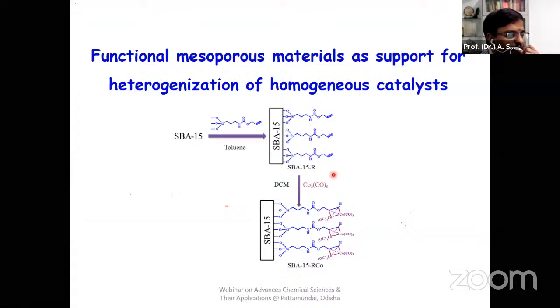But cobalt carbonyl we cannot handle easily. It is volatile, and it is cobalt in the zero oxidation state. It can immediately decompose. So what we did is modify this molecular sieve material with some surface functional group, especially alkyne, that is triple bond containing functionality. The interesting property is that whenever an alkyne moiety is there, metal carbonyl forms bridging complexes.